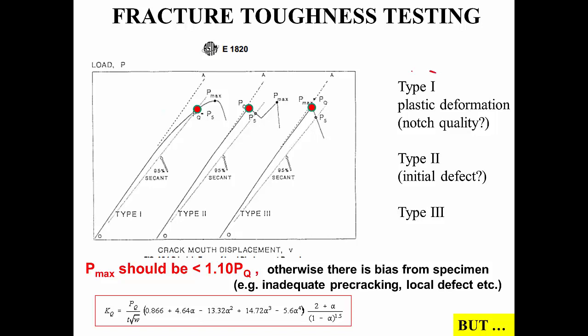In the first case, which I call type 1 here, it is obvious that there is some kind of plastic deformation. Potential sources of this problem are things like maybe a proper crack has not been propagated through fatigue preloading, or sometimes there is too much plastic deformation at the notch. And in order to define the failure load, we have two options. One possibility is to get the maximum load, which is at the peak of this curve.